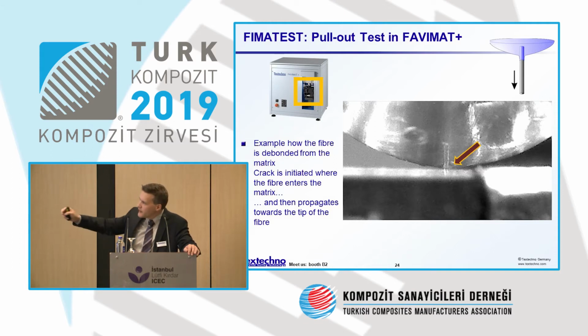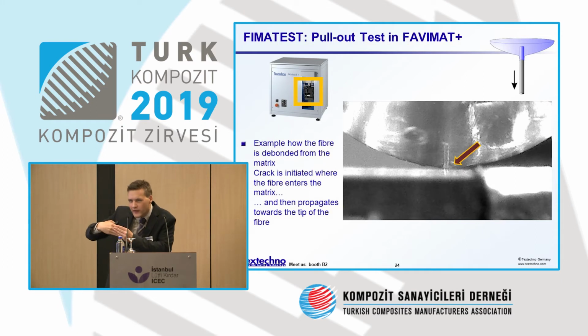You see epoxy matrix droplet pointing downwards, and you see how the fiber, a pretty coarse fiber, is embedded inside the matrix. And if I run this video again, you'll see that as we are continuing to pull on that fiber, at some point there where the red arrow goes, there's a crack forming. We have to wait for a second. There's a crack. And now this crack is propagating along the fiber until it eventually reaches the tip, and now the full fiber has been broken loose and slips out.